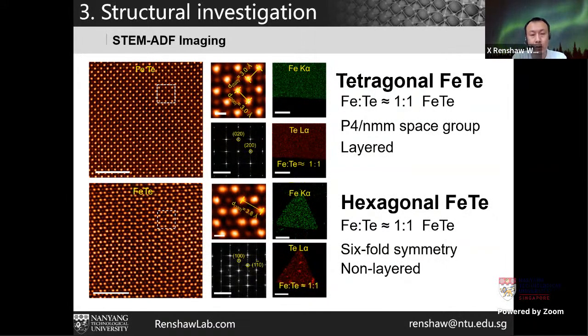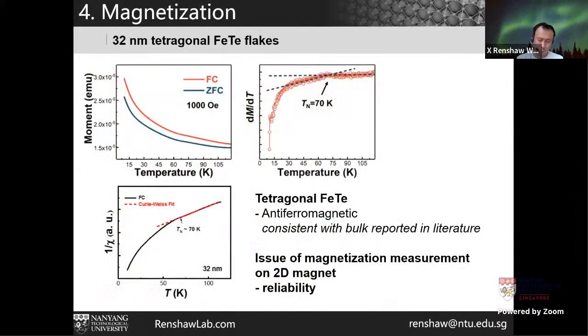Of course, we can also do the elemental mapping. You can see the Fe and Te mapping. The Fe, the iron, is uniform across the whole substrate. I'm talking about the elements mapping in the middle. Also, the Te element is uniform, and the stoichiometry is close to 1-to-1. This is another way to confirm that we are getting a correct stoichiometry. So the structural property is confirmed. We get a high quality FeTe, and then naturally we need to go to the property characterizations.